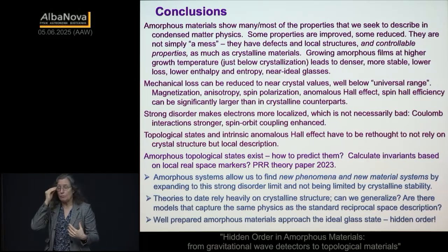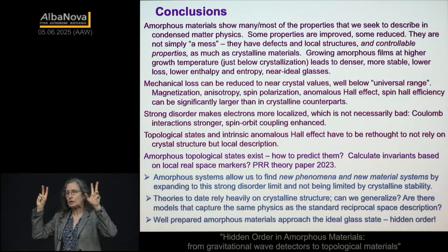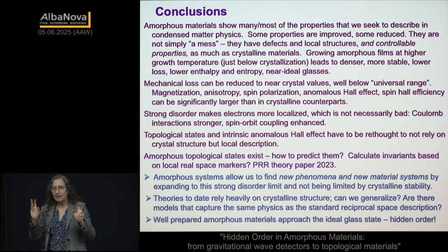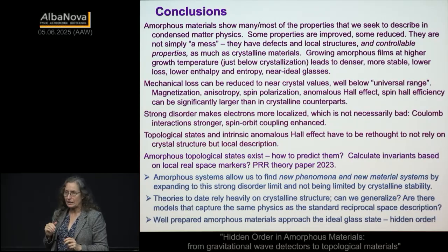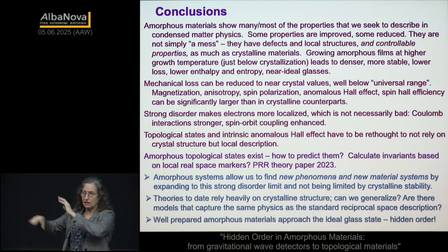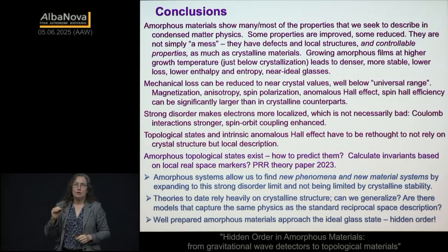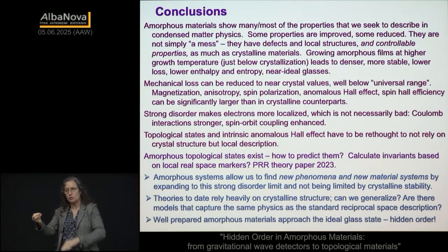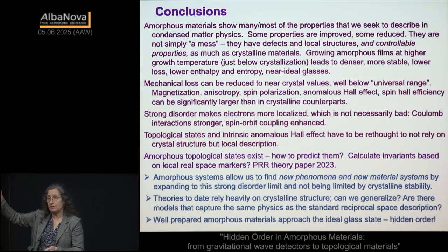I didn't talk about this at all, but I referred at one point to ultra stable. There is starting to be quite a body of literature on using vapor deposition to grow what are called ultra stable glasses, the definition of which is more stable than liquid quenched, by which you mean lower in the energy landscape than liquid quenched. It turns out it also means more resistant to annealing after. So there's a bunch of meanings, but thermodynamically you're lower in the energy state. So you can see that in things like the glass transition. If you grow at a higher temperature, you're lower in the energy landscape. Therefore, you have more energy to release when you go through the glass transition. You're going further, you've got more energy available.